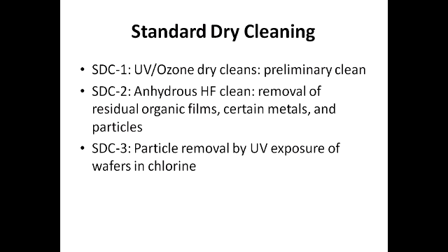SDC2 is an anhydrous hydrogen fluoride clean, removing organic films, metals, and particles. SDC3 removes particles by UV exposure of wafers in chlorine.